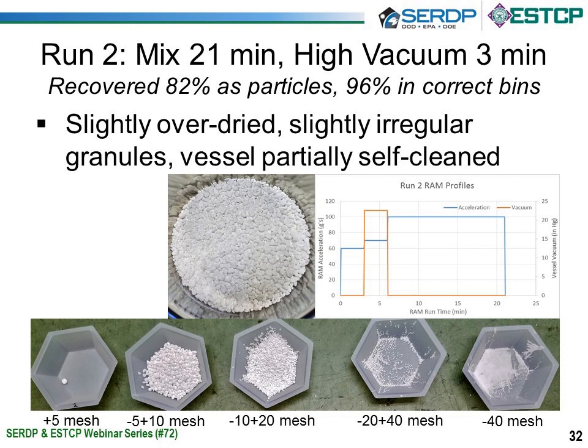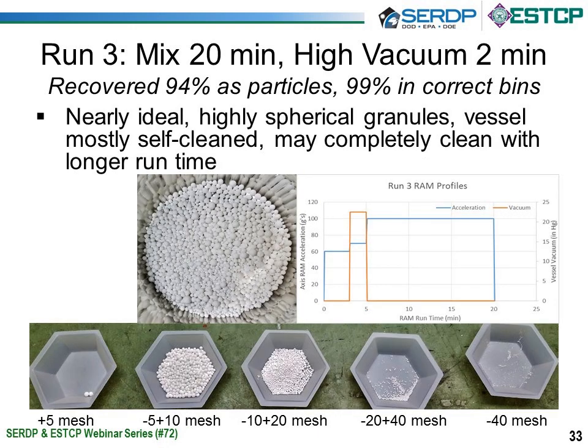Slide 33, please. For run 3, we reduced it to 20 minutes by reducing the high vacuum duration to 2 minutes. Again, 3 minutes for wetting, 2 minutes for high vacuum, and then the remainder at 100 Gs for the rounding and polishing. And as you can see from the results here, we got nearly ideal, highly spherical granules. The vessel was mostly self-cleaned because we were able to recover 94% of material as particles. And more importantly, 99% of those were in the correct bins, as shown.